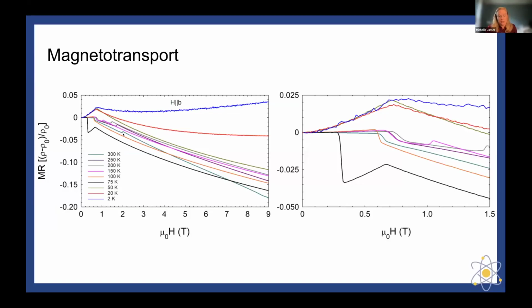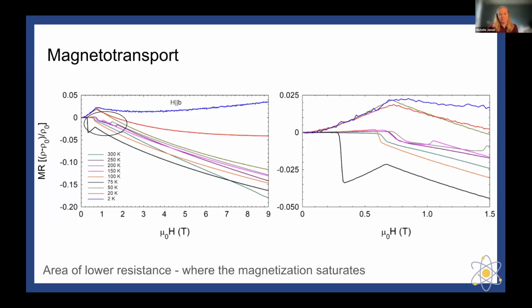That's a change in the resistance state. So where we see that there is an increase and then a sharp decrease in the magnetoresistance, that's actually where you're in the transverse conical state. So it actually causes a huge change in how your electrons are moving through the material with applied field after you are in that antiferromagnetic state. And then right where the area of lower magnetoresistance drops out, where you start to see that increase again, that is where the magnetization saturates again. So that's when you're in that ferromagnetic state after you hit a certain field.